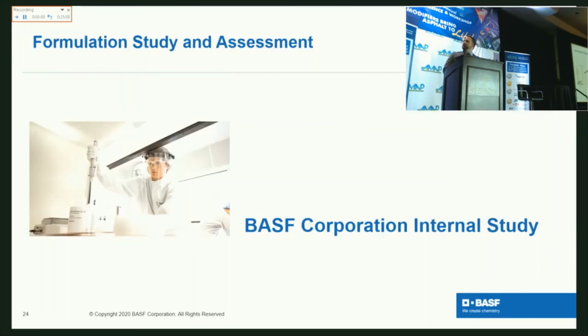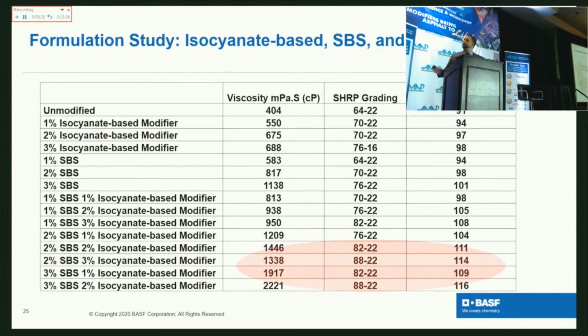So from there, internally we wanted to look at, again, the interactions with SBS. What happens when we use it in conjunction, because with isocyanate-based material, you don't get the elastomeric properties that you do from SBS. You do get some, but not as much as we're looking for with a normal specification. Again, that's my point with the rubber ball. It's a different paradigm. So in conjunction with it, what could we do?